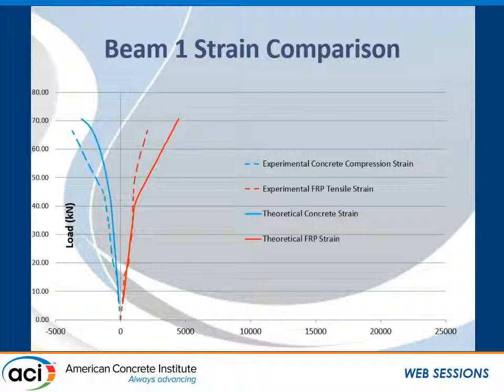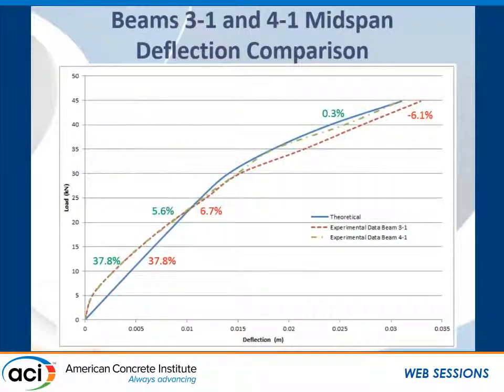And then those moment curvature diagrams were used with the virtual work method to predict the load deflection behavior up to ultimate load. And I'll show you one of those examples here. Theoretical midspan deflections were compared to experimental deflections from the beam tests. And as we see here, the predicted deflections for the beams from the 2007 tests are consistent with the experimental results, particularly at service load levels, but also at ultimate loads, where the difference was approximately 6%. That corresponded to an absolute error of only 1.9 millimeters.